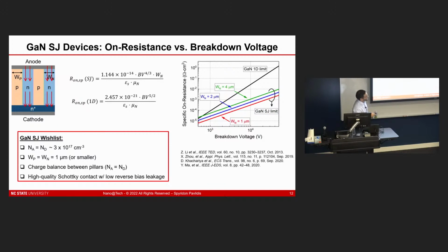Clearly, if I can scale these devices down to smaller pillar widths, I can see even more benefits in my performance. So we have to think about ways that we can control doping, control the incorporation of doping in different regions, but also, can we do this in a way that can be scaled down to very small pillar widths? If we do that, then we can improve the performance of our devices. And so we're looking at trying to make these 1 micron pillar widths, or potentially even smaller in the future. And like I mentioned earlier, engineering the various parts of the device here.